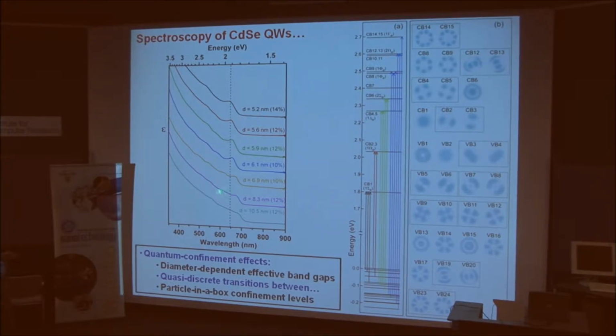You can also see a number of additional features in these spectra. They're not real clearly resolved, but those are all due to the fact that the electron and hole wave functions in a cylindrical quantum wire behave as though they're trapped in a cylindrical box. And that's pseudo-discrete energy levels, particle-in-a-box levels in the wires. And all these additional features can be assigned to various transitions between these particle-in-a-box states. And these only exist because of quantum confinement.